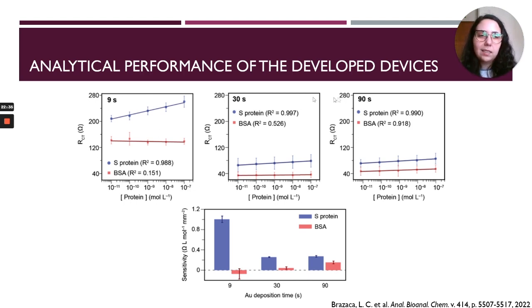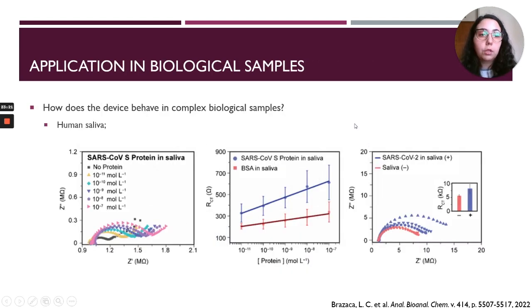If we go to 30 or 90, we do see that the behavior is quite different. So for 30, we still have some differentiation between S protein and BSA, but for 90 seconds, the curves start to overlap. This can clearly be seen using this graph on the bottom that shows that the sensitivity of the curve for S protein decreases from 9 to 30 to 90 seconds of electrodeposition time, and for BSA, the sensitivity increases. So the condition that provides the most difference between the two proteins is 9 seconds, and this was chosen as the ideal one to go forward and to do some studies on actual biological samples which are used